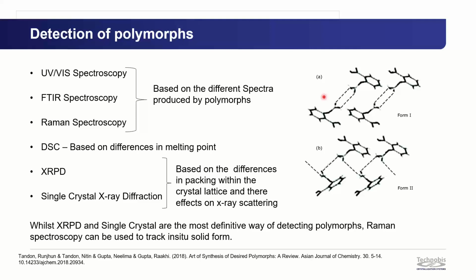DSC is based on thermo properties, so this can be that different polymorphs have vastly different melting points. It is possible to see melts and recrystallizations using DSC. And then finally, XRPD and single crystal X-ray diffraction, which is measuring the diffraction pattern of X-ray scattering within the crystal lattice. And whilst XRPD and single crystal are the most definitive ways of detecting polymorphs, Raman can be used to track in situ solid forms, so being able to detect what's going on.